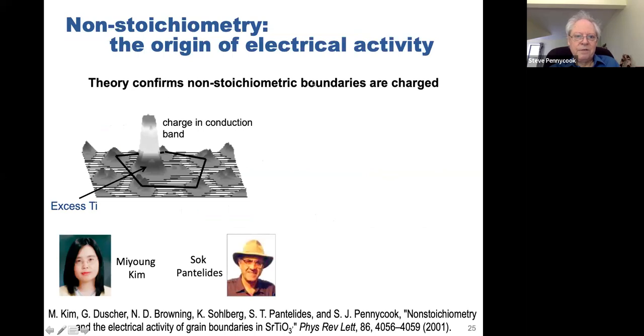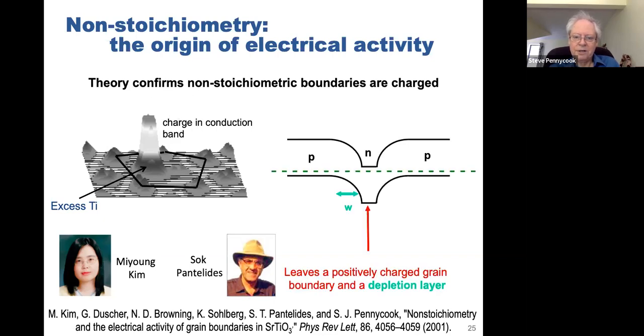So carrying on with the story, our favorite material, strontium titanate. We figured out eventually that these so-called pairs of columns, it was pretty obvious they couldn't be fully filled because they were too close together in the dislocation cores. And Sok Pantelides became a regular visitor to my group, doing density functional theory, and Miyoung was also a postdoc, also doing density functional theory. Eventually we realized that it's the non-stoichiometry at the grain boundary that is the origin of the electrical activity. And so you deplete the boundary of oxygens and you get positive charge left behind, setting up band bending and a depletion layer.